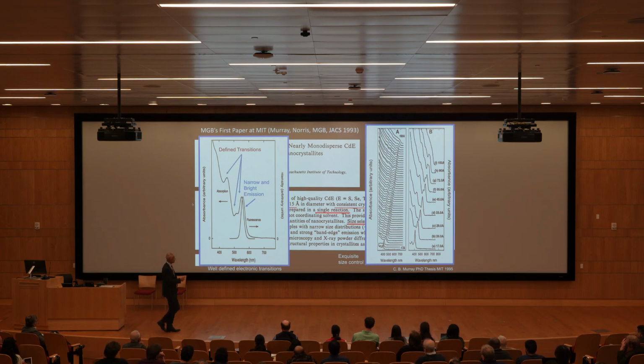And Chris, in his thesis, has this progression of spectra. So this is blue here, and this is red here. These are tiny 1 nanometer particles, and as you grow the particles, they march across the visible as they get bigger and bigger, and the energy of the wave gets smaller and smaller. And this is the bulk, right down here. By the time we're at 15 nanometers in size, with this experiment, it looks like a bulk.